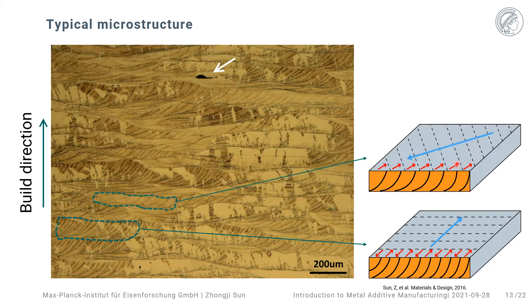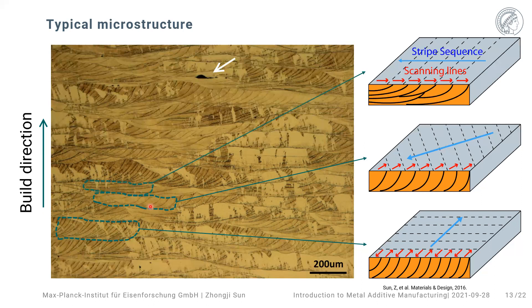In AM production, typically for each layer there is a 67-degree rotation to minimize accumulated residual stress. With rotation, although the laser still moves back and forth, the average distance between each laser track on the viewing plane is spaced out, so the melt pool boundaries are slightly further apart. If we continue adding another rotation, there is a situation where all the laser lines are somewhat parallel to the viewing plane, which is why we see lines stacked on top of one another.